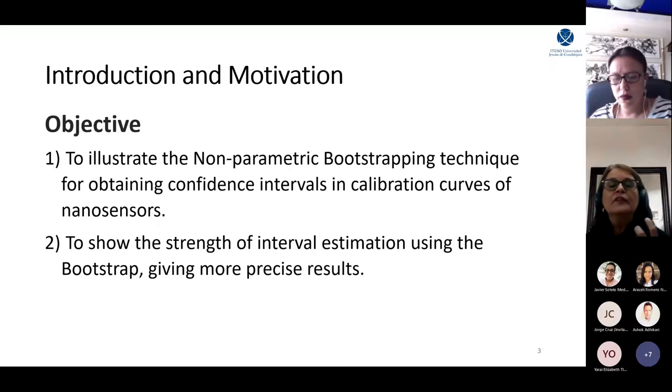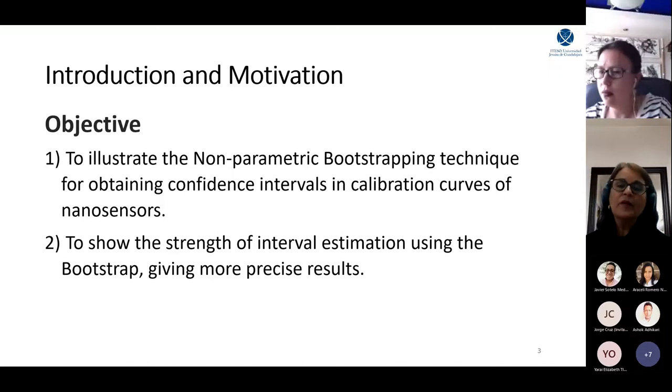We tested the sensor response with five different concentrations of hydrogen peroxide in millimoles. Also, we use two types of metals for the sensors, nickel and gold. Furthermore, we apply two different geometries, nanowires and planar. The planar geometry is for comparison, because it represents the more extreme case of the non-nanostructured sensor.